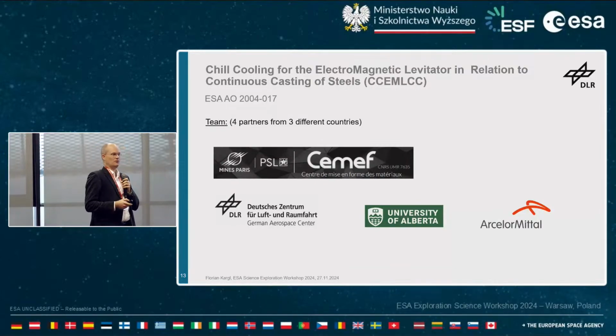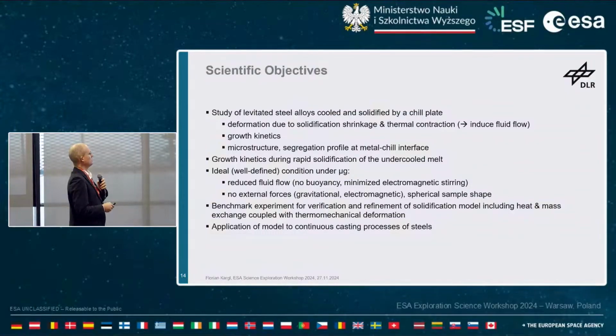So going to another project now, CCEMLCC, which is more into an application, which is in the area of electromagnetic levitation work, looking into chill cooling with a relation to continuous casting of steels. This is done by 4 partners from 3 different countries, headed by Charles-André Gandin from Mines ParisTech in Sophia Antipolis, who does a lot of modeling of the process and then space station experiments. The idea is to study the levitated steel alloys, how they cool and solidify when they get into contact with a chill plate. We will see that there is deformation happening due to solidification, shrinkage, and thermal contraction, and that induces fluid flow, and that has an impact on growth kinetics, microstructure, and the segregation profile at the metal-chill interface.